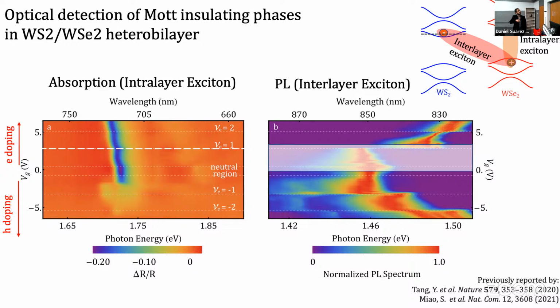So this first measurement is an absorption measurement. So it tells you about the available states in the system. You basically shine white light and you see the light that is being absorbed. And in this case, it is the emission, so the occupied states in the system. It is a photoluminescence experiment. So you excite out of resonance, and then depending on the particles that you have in your system, you will collect the optical emission from there.